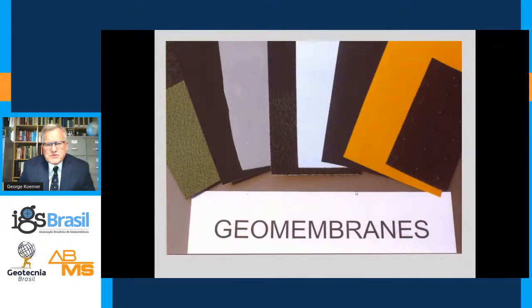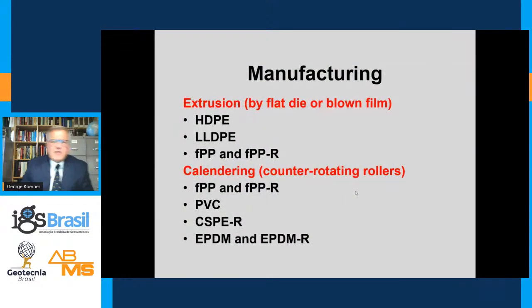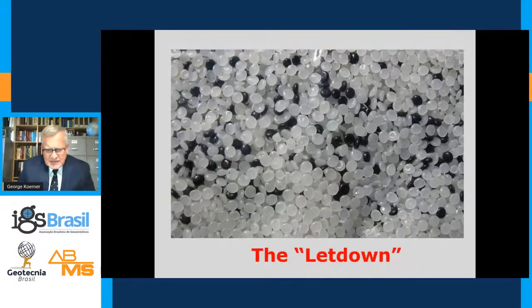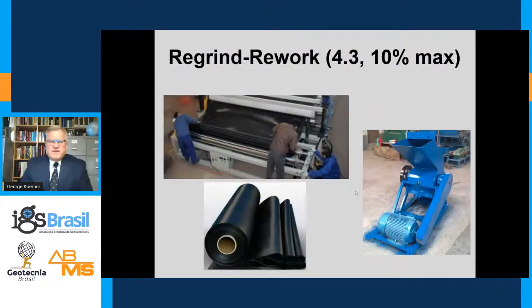Now we'd like to produce that geomembrane. And to produce that geomembrane, you typically have extrusion processes or calendaring processes. The olefin plastics that we showed you are the extrusion, flat die and blown film, and we'll show you both of that. As far as the calendaring process is concerned, that's typically PVC and also the scrim reinforced materials. So we take the resin and the concentrate, which is the carrier resin, and the additive package and the carbon black, and then we have to make sure that we address regrind or rework.